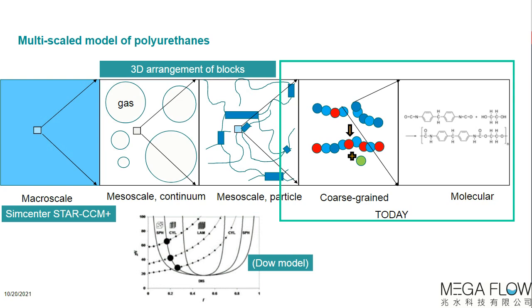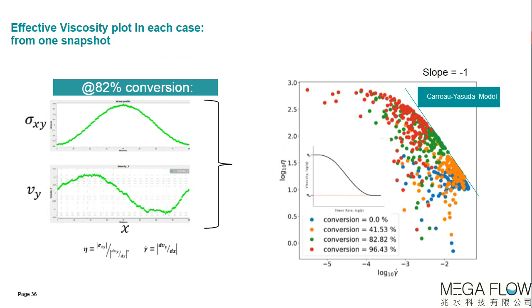And then, the same as in the Kevlar, we calculate the stress and the velocity profiles in the system. What you saw in the Kevlar were these plots of stress and velocity. Well, the two of them, as I said, are what you need to get a constitutive equation. So you can formally define an effective viscosity simply as the ratio of the stress and the velocity gradient. So there's the strain rate here, the gamma dot, which you can actually calculate from the gradient of the velocity profile. Supposing you have done an accurate enough calculation and not too much noise, then you can actually do this as a function of conversion.